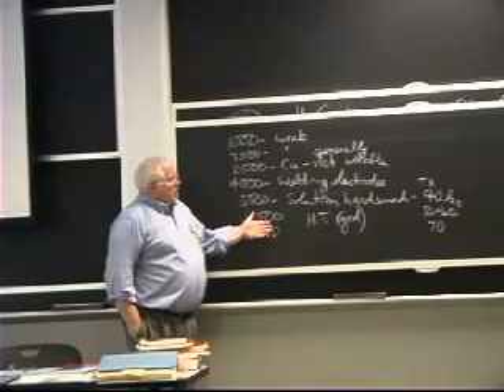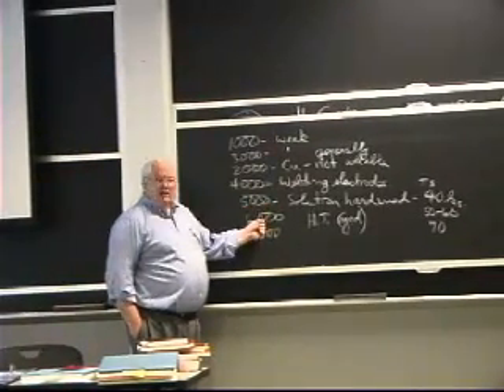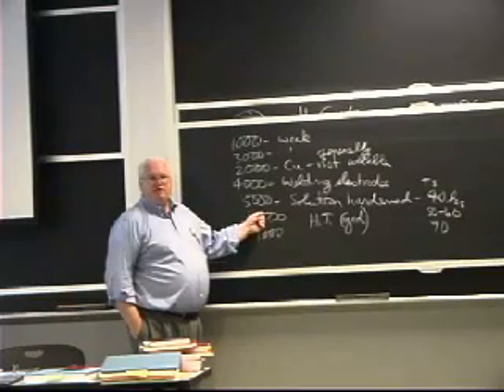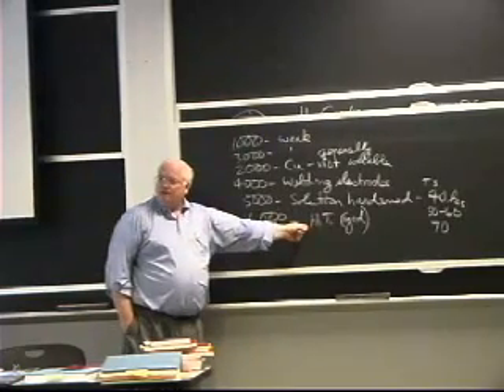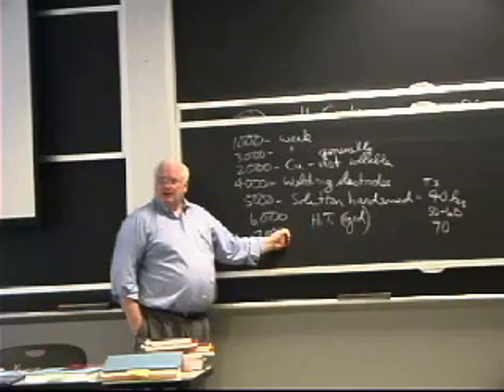The 8000, I think, includes the aluminum lithium alloys for aircraft structures. Anyway, you can weld these and get 100% strength. These, you're lucky to get 50% strength because the heat affected zone gets unheat treated, okay, by the welding process. So if you do fusion welding on these guys, you're out of luck. You won't get full strength.